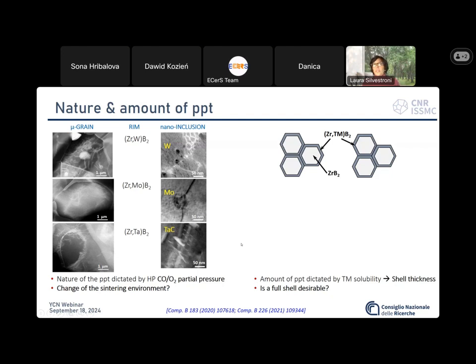We also wondered if having core shell grains made of complete solid solution, like eliminating the core, would be more beneficial than the core shell structure. But the answer is no, since the elimination of the core and the formation of a homogeneous shell mean the elimination of one discontinuity, that is the dislocation walls present at the core shell interface. And actually, these linear faults are conducive to a grain refinement and to increased plasticity upon testing at elevated temperature.